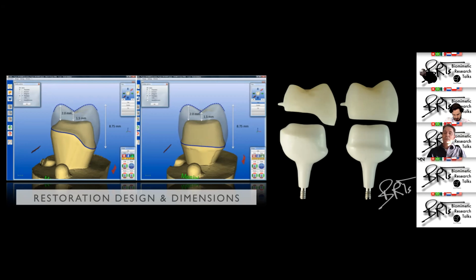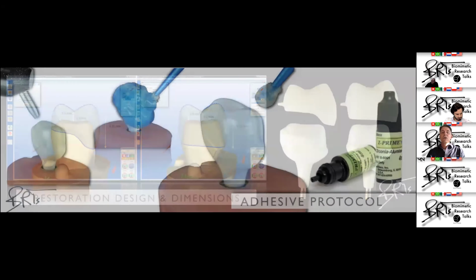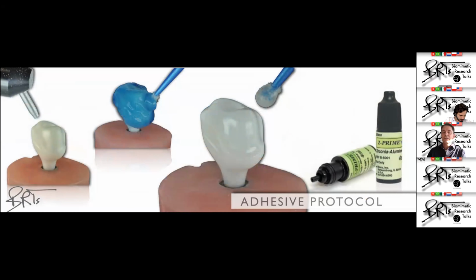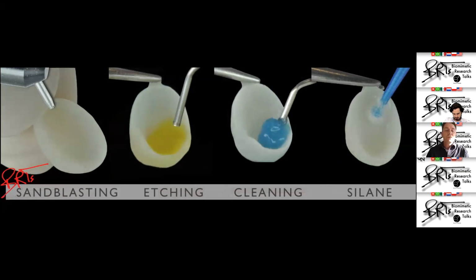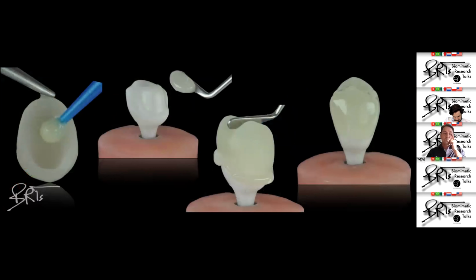Once the restorations were done over the zirconia abutments, we bonded them following the adhesive protocol. First, on the zirconia abutment, we sandblast and etch for cleaning and apply the zirconia primer, Z-Prime, and light cure for 20 seconds. On the ceramic restorations, we etch and sandblast. On the composite resin restorations, we did the same, except for the hydrofluoric acid. For luting, we used OptiBond FL and preheated composite resin. After cementing, finishing, and polishing, the samples were ready for loading.